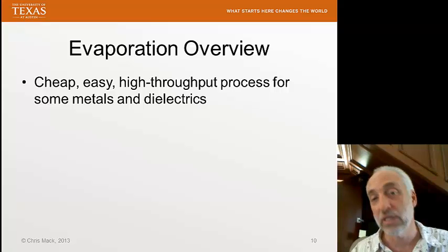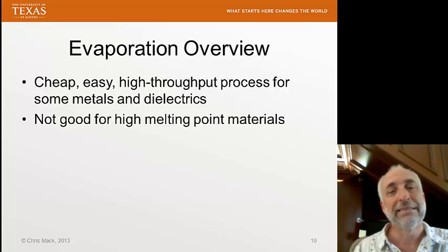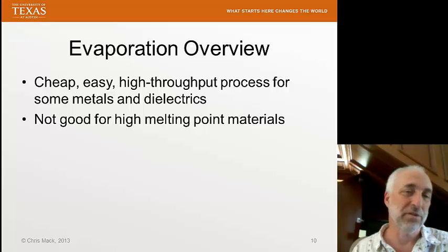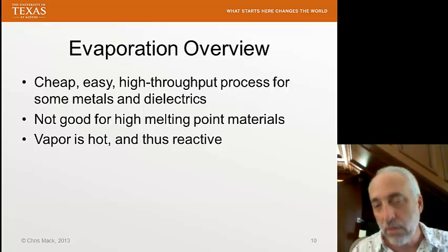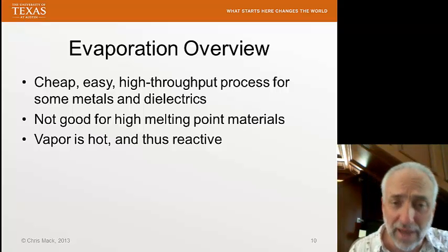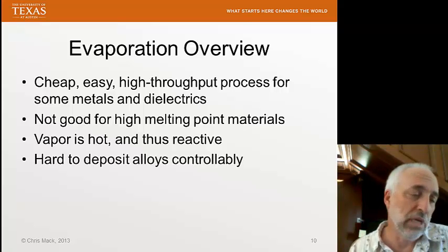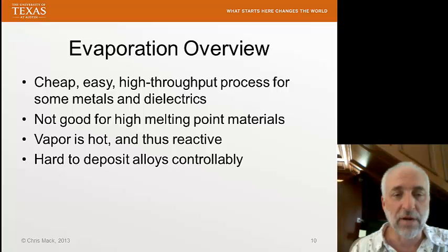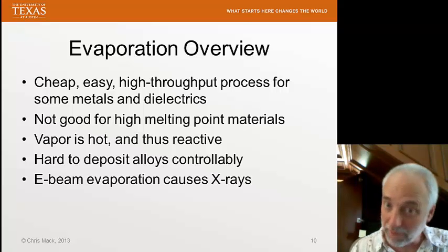It has the ability to evaporate lots of different materials as well. It's not very good for high melting point materials, though. The vapor is hot and thus reactive, which means I have to operate at low pressures, which means I have this line of sight deposition, which makes it difficult to get good step coverage. It's hard to deposit alloys controllably.